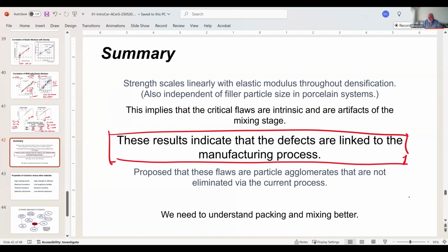Strength scales with linear elastic modulus throughout densification. This is a huge observation, because it says that my flaws are intrinsic and are artifacts of the mixing process or the process itself. In other words, in a given factory, I have the same flaw population for my material going through. Based on work that we've done subsequent to this, we would propose that those flaws are particle agglomerates. They're almost never inclusions, but they could be particle agglomerates, in other words, clusters of material that come in with raw materials that need to be eliminated in the process in some form.